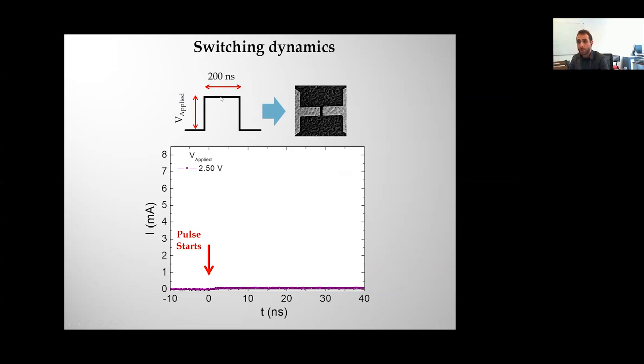So we send 200 nanosecond pulses to this type of device. And here you have current that goes through the device as a function of time. The pulse is applied at 0 nanoseconds. And you see that current raises a little bit, but not much, because the device remains in the insulating state. But if you increase the amplitude of this voltage pulse, what you see is that above some threshold voltage, what we call the threshold voltage, you're actually able to induce a transition into the metallic state. And you have that your material now becomes metallic and conducts, so the current goes up. But that doesn't happen immediately, and you can see that there is some incubation time.